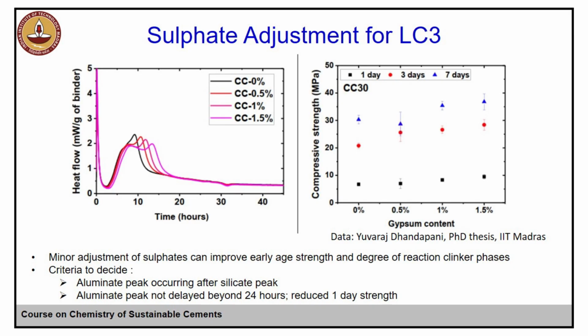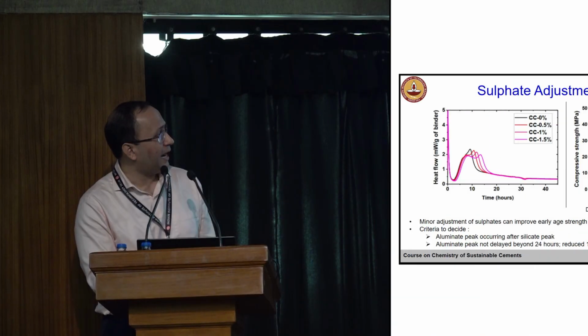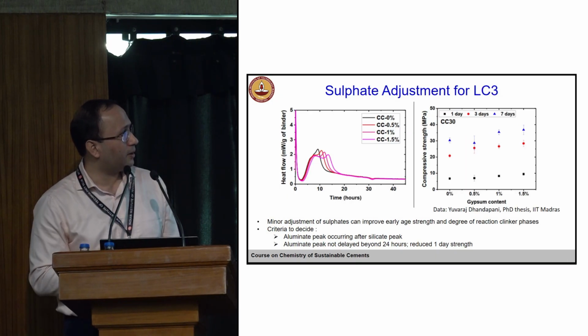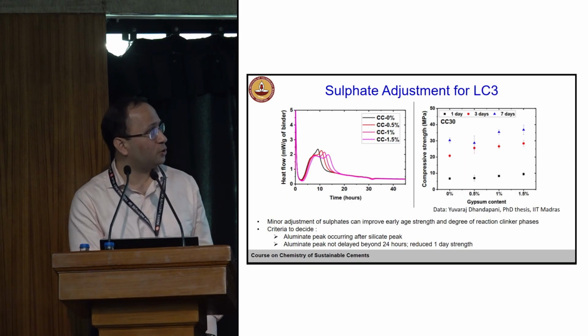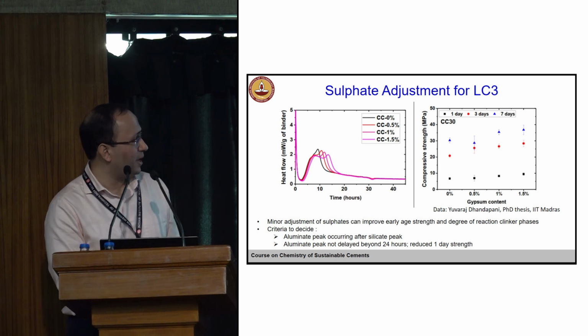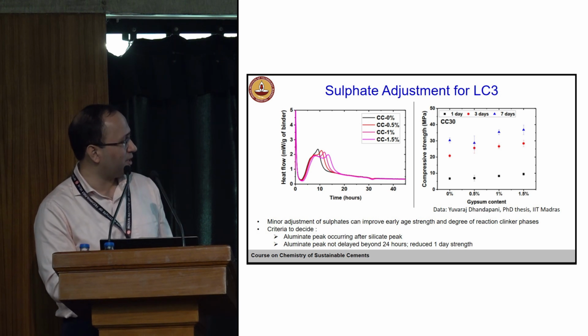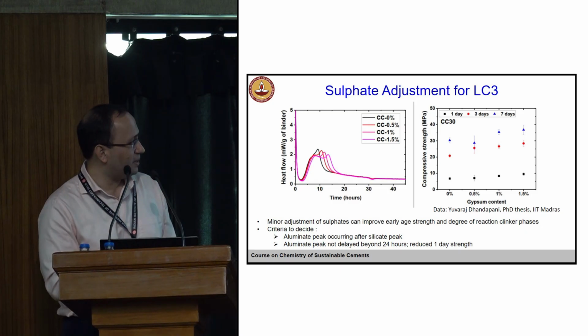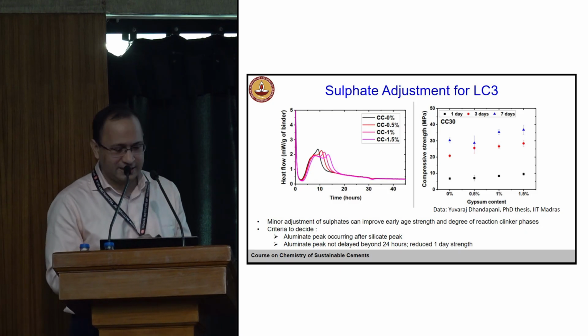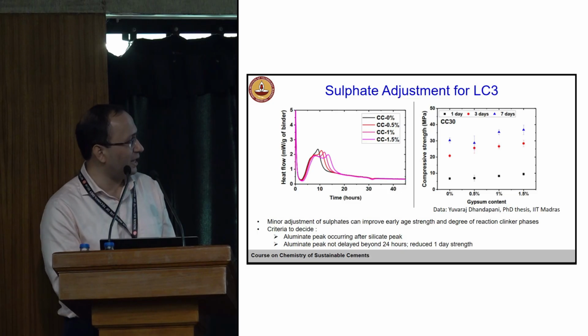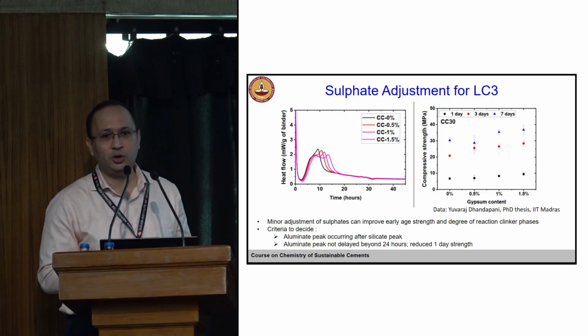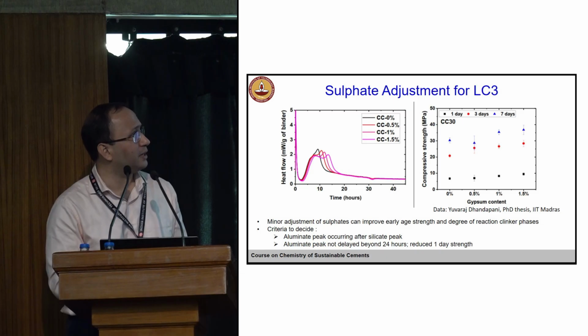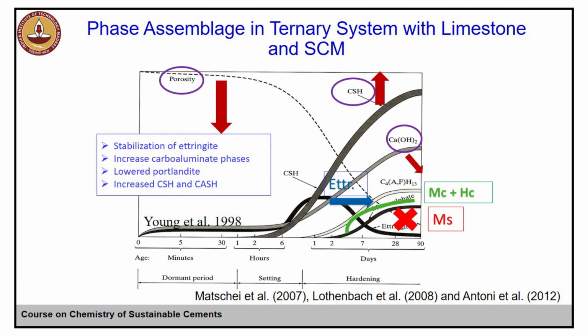Another example showing you how gypsum addition can be used and what its impact is on the strength, right? So we can also look at the impact on the strength. What is the criteria to use? Basically, aluminate peak occurring after the silicate peak, and also aluminate peak not delayed beyond 24 hours. Otherwise, we'll have reduced one-day strength. So this is some of the things we can keep in mind. Yeah, so this was again shown by Professor Shashank.